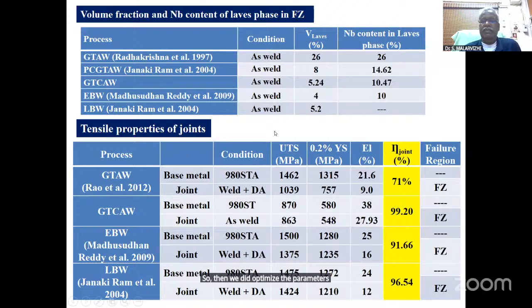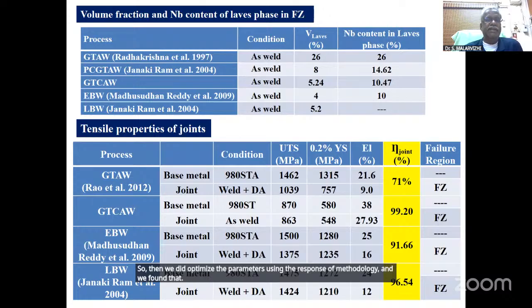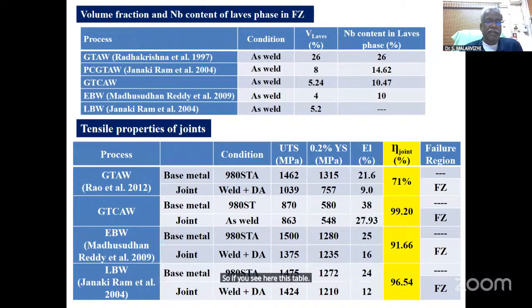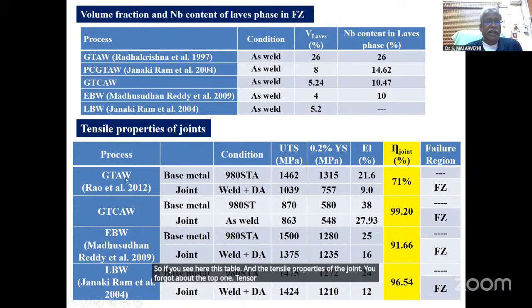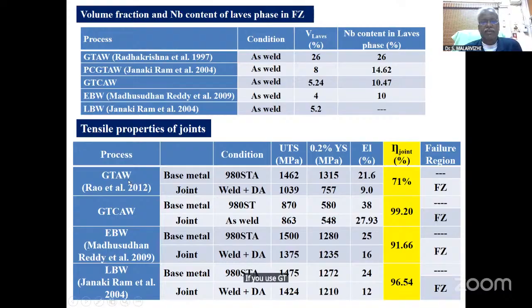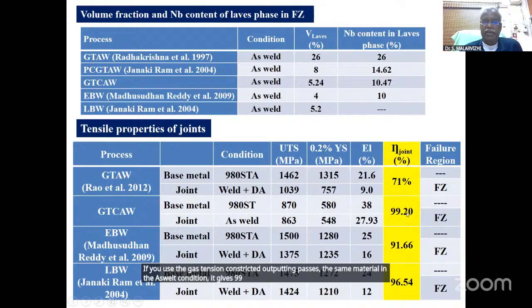Then we optimized the parameters using response surface methodology, and we found this. If you see this table on the tensile properties of the joint, forget about the top one. If you use GTAW, the conventional TIG welding process, the joint efficiency obtained is only 71%. If you use the gas tungsten constricted arc welding process on the same material in the as-welded condition, it gives 99.2%. It's almost matching the base material strength.